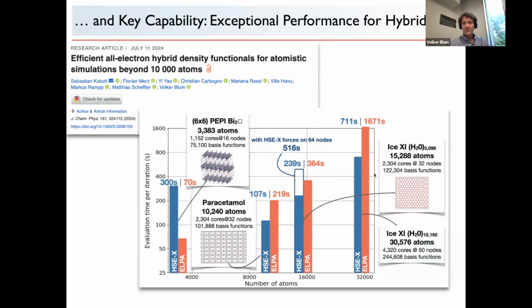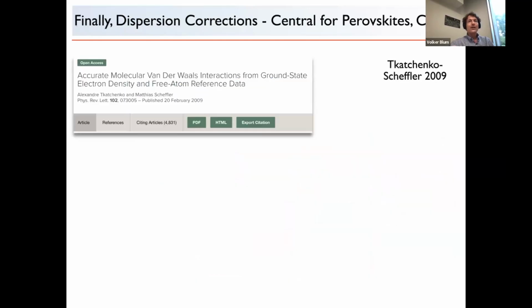Well, this is 15,000 atoms, an ice crystal, and we can do something like 30,000 atoms in an ice crystal as well, which is then the largest system with hybrid functionals that we are aware of in a direct calculation that has been done. But it actually works, and we're quite proud of this, and this works with reasonable effort compared to what was possible before, because we didn't think this was possible. So that's the hybrid DFT part.